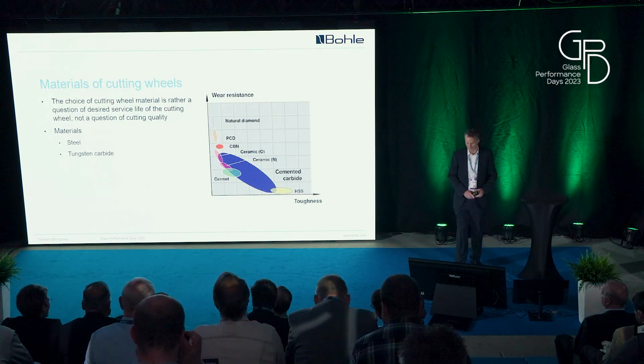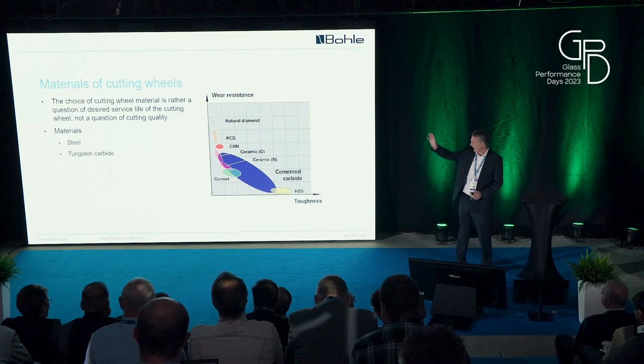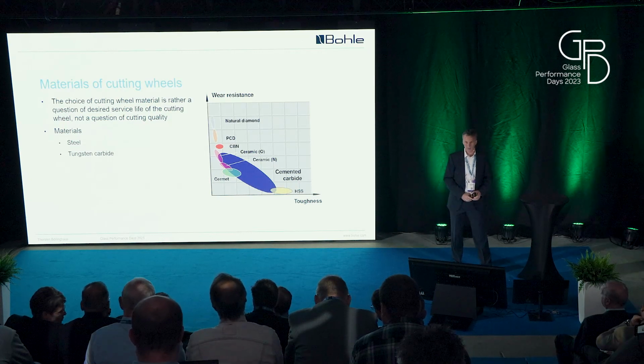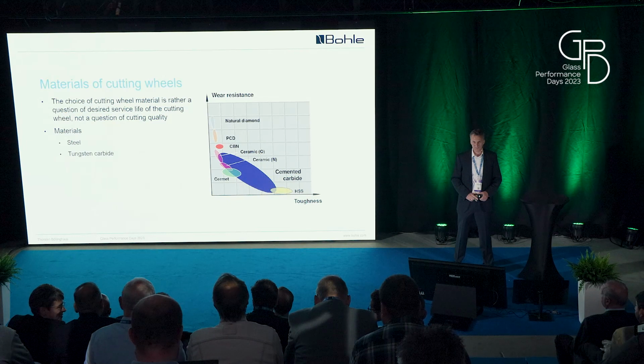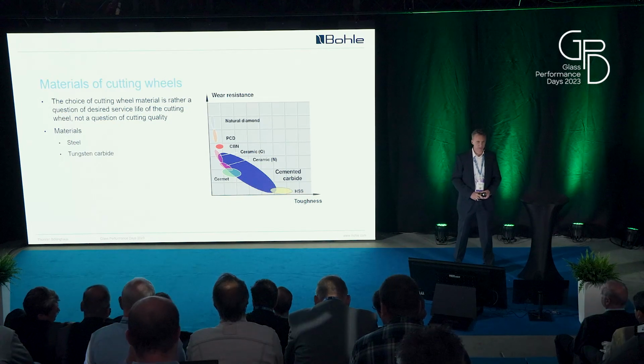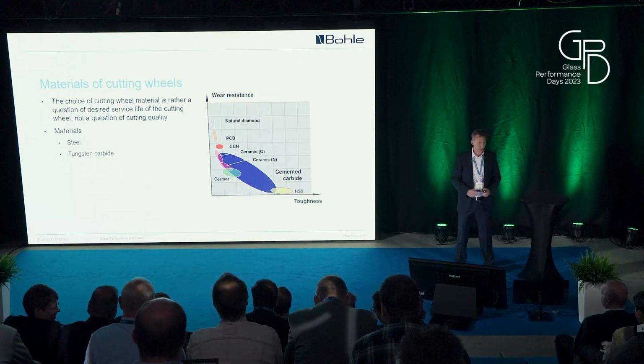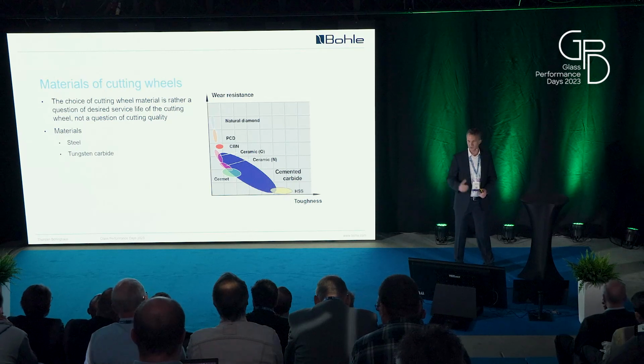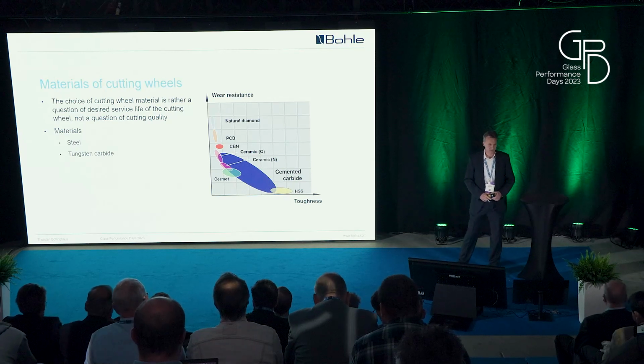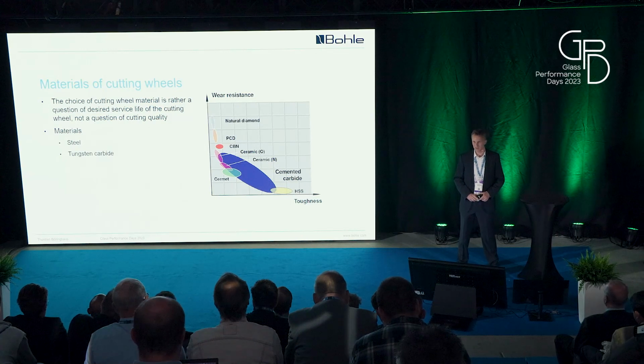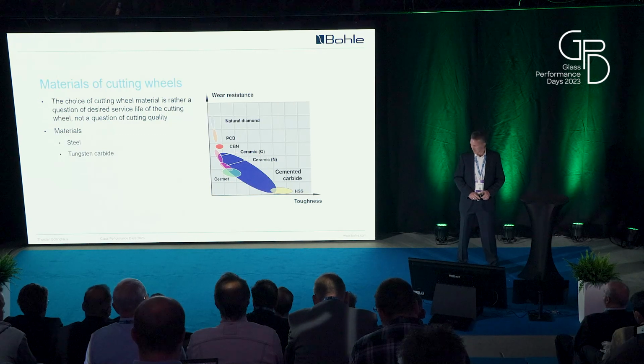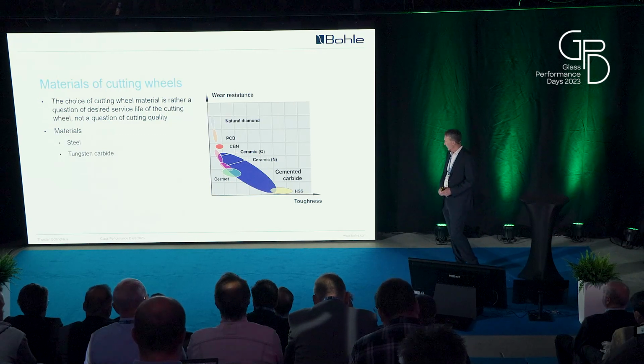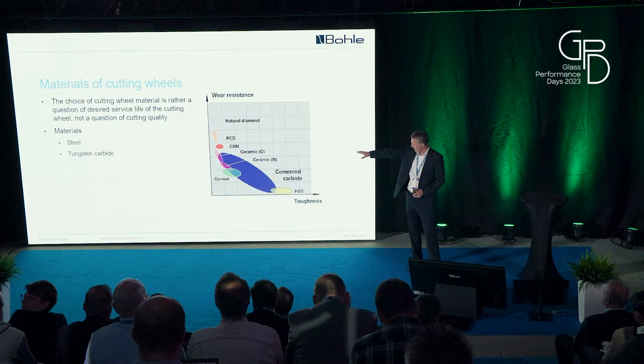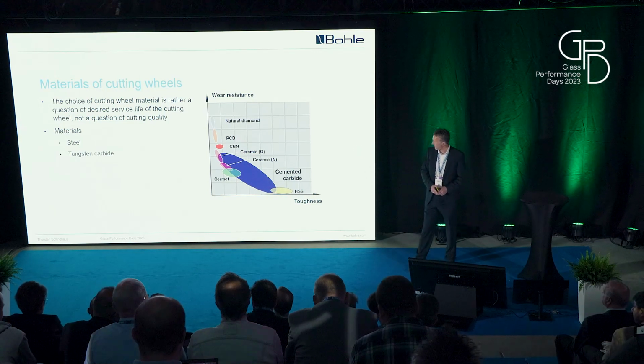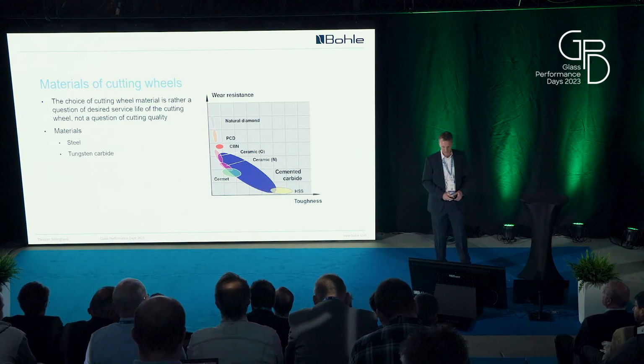And if you compare wear resistance, which is hardness, and the toughness, that's the zone it covers. Toughness is very important because in industrial glass processing, when you're not in the laboratory, you can hit your glass with high impact. So for the stability of the cutting wheel, it's important also to have the toughness of a wheel. So cemented carbide or tungsten carbide covers quite a zone, and cutting wheels are rather in the upper part or in the highest part of it.